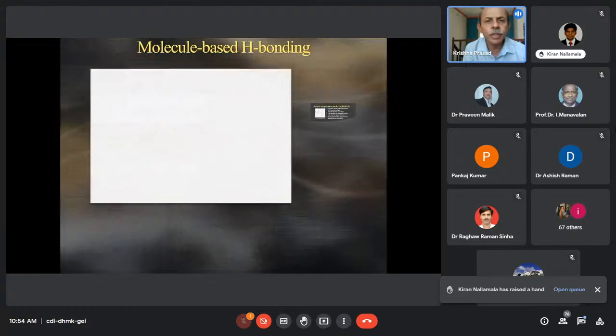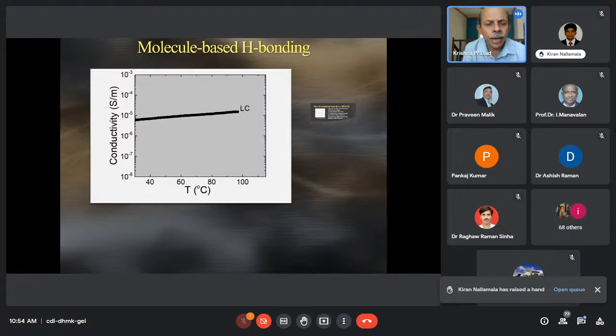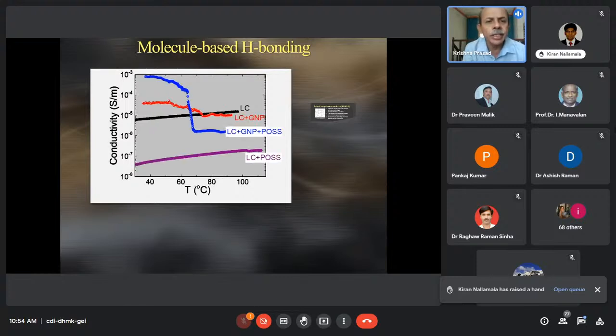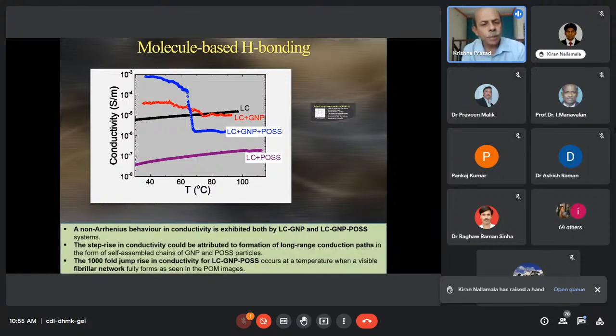I won't go into the details of this, and probably I'll skip this topic because of lack of time. You can do a similar kind of thing with molecular-based hydrogen bonding systems as well, and you can increase the conductivity by significant orders of magnitude, and also change the temperature dependence, going from a truly Arrhenius, which should be true for liquids, to a ballistic kind of electron transport that is characteristic of hard systems and not soft systems. I won't go into the details of that.